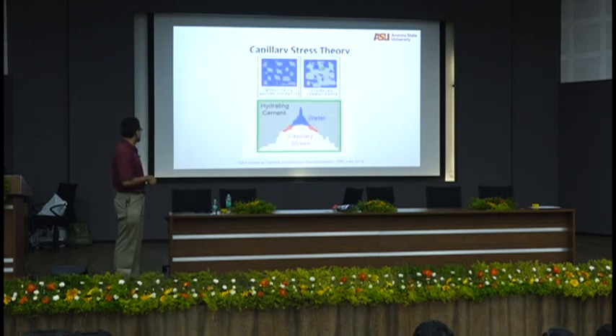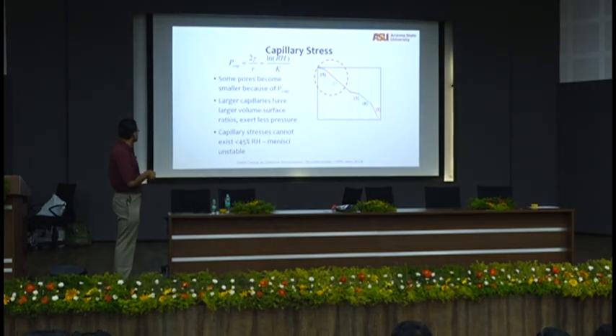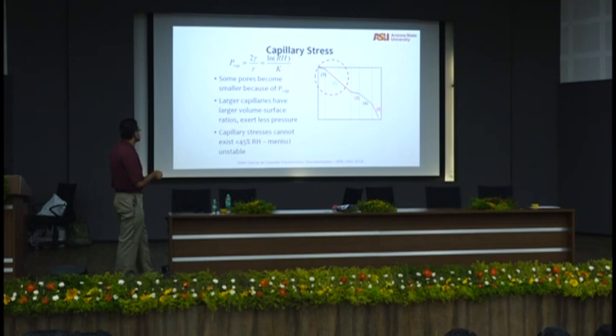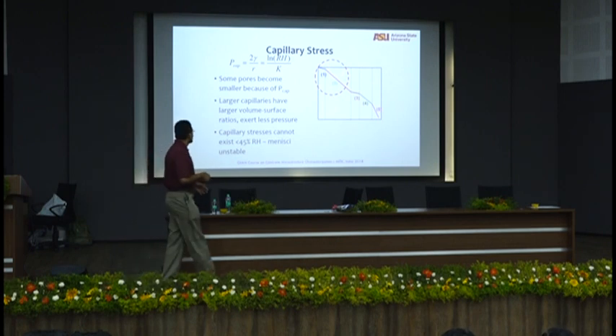So basically you have hydrating cement, you have water in the pores, capillary stress, you dry the water off, and then the simple equation, capillary pressure or capillary stress is 2 times surface tension over the radius. Again, pressure is inversely proportional to the radius. It can also be given as the natural logarithm of the relative humidity divided by a constant K. I have told you where this is happening in that curve, right? In the stage 1 and 2. Capillary stress very early on.